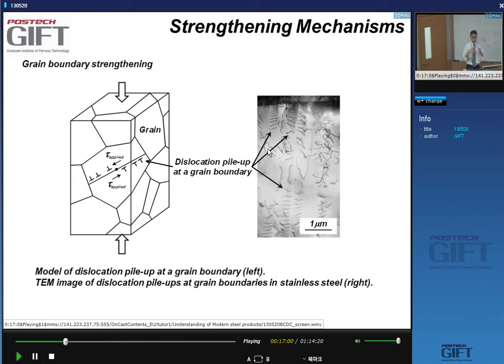And the smaller your grain is, if the grain is very small, then you don't need to have many dislocation loops before you reach this situation. So the smaller the grain size, the higher your applied stress must be to have plastic deformation of the grain, because the dislocations are stuck at the grain boundary. Right? And this is a real effect, it's a very strong effect, these grain boundaries.